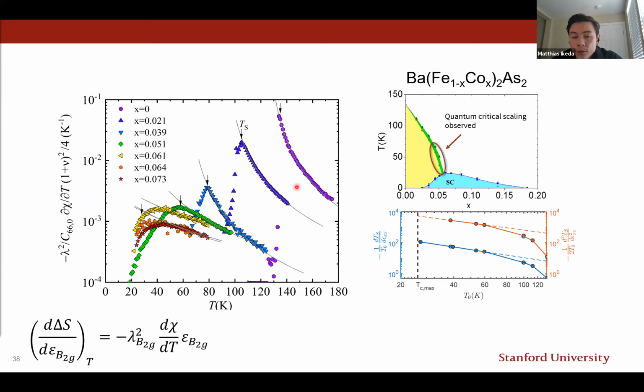to critical phenomena. We find features around the phase transition temperatures, but the background contribution from lattice degrees of freedom is extremely small. And that's small across the phase diagram. It's in fact significantly smaller than any of the data that is shown on that plot. So it's very unlikely that any of this data here is dominated by response from the lattice.